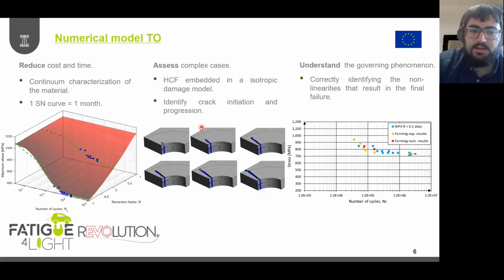By using the numerical approach that we are proposing, we are moving from this commonly used strategy towards a strategy in which we combine the fatigue degradation coming from the application of cycles in a geometry with an isotropic damage model that allows us to identify both the crack initiation and also the propagation of that crack along the life of the material. So we are able to take into account changes in the loads being applied along the life of the material, which may generate a complex evolution of the crack that causes the final failure of the